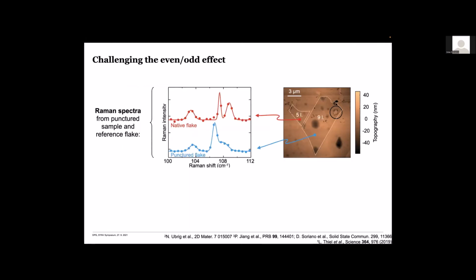And the reason for this is something that Rainer already alluded to some extent. It has to do with the stacking order of these different parts of the flake. And we were able to really verify that using Raman spectroscopy that we performed on these 2 parts of this flake. So again, the good thing here is that these were separated with a 5-layer part, which was decoupled from the 9-layer part. And you see here that there are, well, weak, but still clearly distinguishable differences in the Raman spectra emerging from these 2 parts of the chromium triiodide flake.